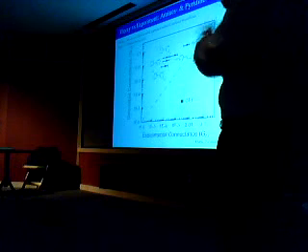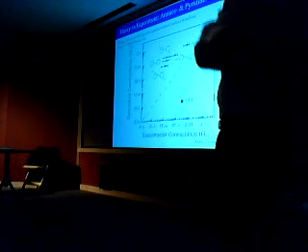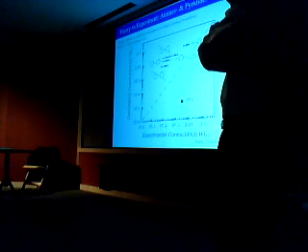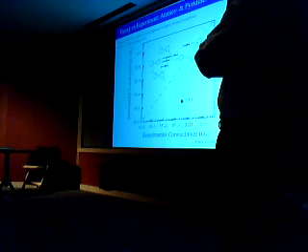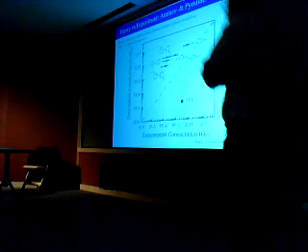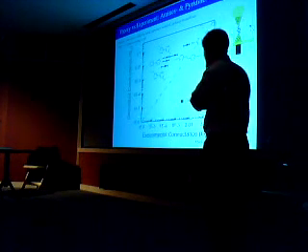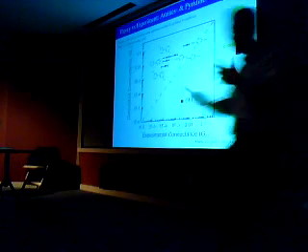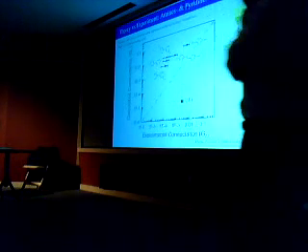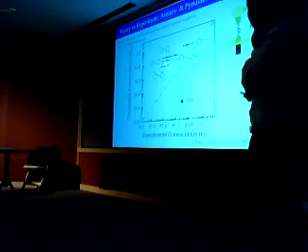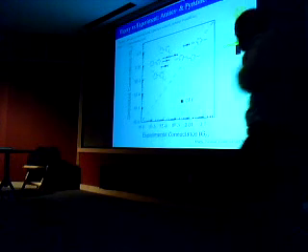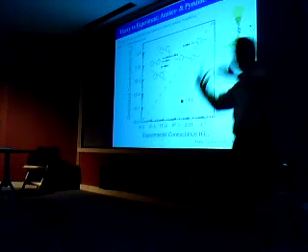So let me just show you some results as a consequence of this kind of quasi-particle correction on the conductance of transmission through a molecule. This is for a series of molecules that we have looked at, comparing the calculated conductance with the experimental conductance. The calculation is done using the Landauer formalism. And you see that the calculated results are in general an order of magnitude too large compared to the experiment.